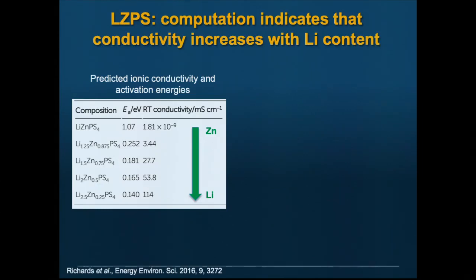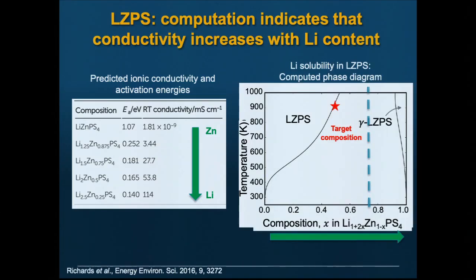So remember, that's a factor of 10 above the best known solid-state lithium-ion conductor there. But as always, nature is against you, right? And so it turns out if you calculate the phase diagram, this is LZPS. This is a solubility limit. This is the lithium content. Our target composition, the optimal composition, is right in the two-phase region, right? So if anything, we would have to make a really metastable compound that sits in the two-phase region. So we have never been able to actually get to that composition.